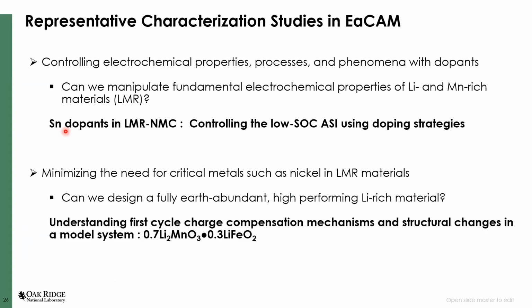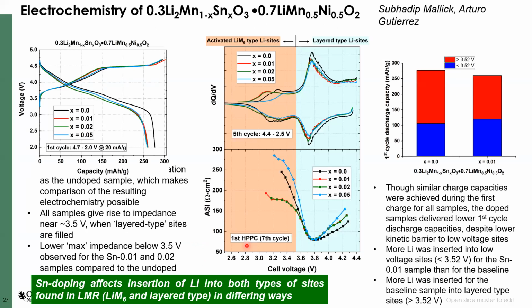It turns out one of the properties we want to control at the low state of charge is what is called the area-specific impedance. And we are trying to see if we can do this using doping strategies. The other one is more fundamental work, where we are trying to see if we can make a lithium-rich material which is completely devoid of nickel. So we are trying to see if we can make materials based on manganese and iron. So I'm going to show some of the fundamental work we are doing in it.